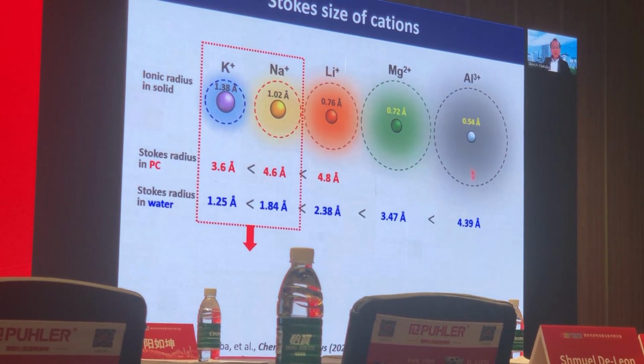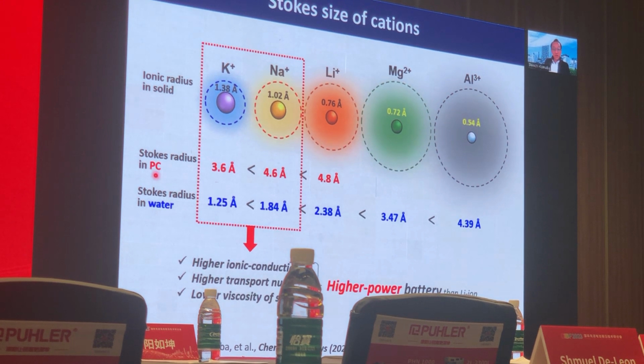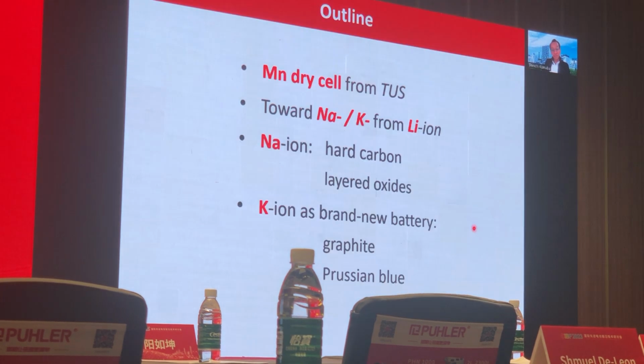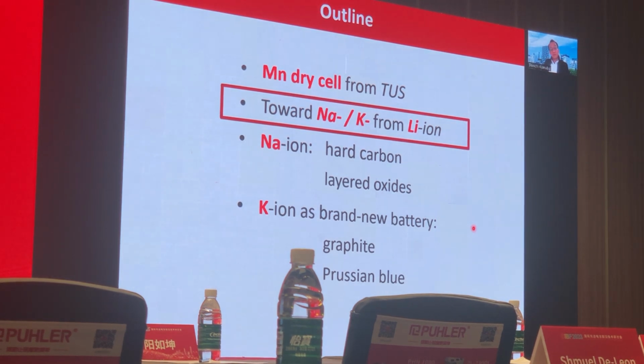Actually, comparing the hydrated size and also the crystalline ionic size, potassium shows a larger ionic size, but potassium shows the smallest Stokes radius in water or organic electrolyte solution, so that potassium and sodium show higher conductivity, higher transport number, and also lower viscosity than lithium electrolyte solution. These features are remarkably advantageous for high power batteries compared with lithium ion. So this is the outline of my talk, and first, I will emphasize the motivation towards sodium and potassium batteries beyond lithium-ion batteries.